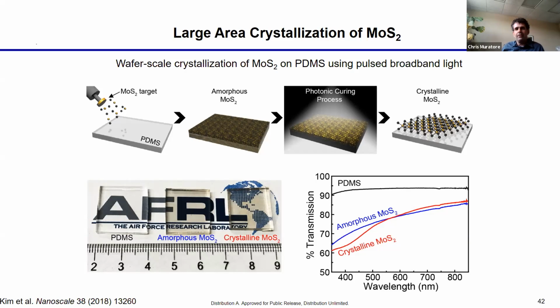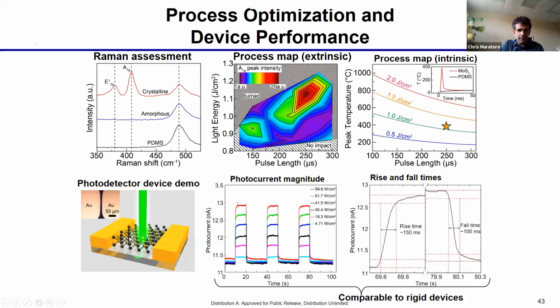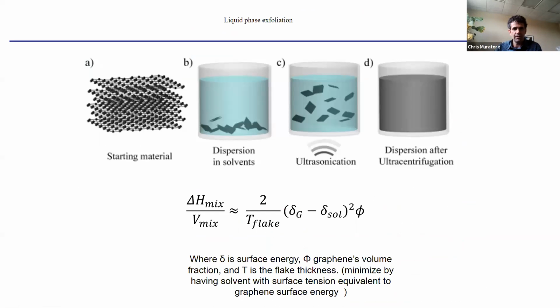You don't have to use a laser. You can use a broadband source, like a xenon lamp, as an optical source. And you can expose the amorphous material to energy in the form of this light and crystallize it over a much larger scale simultaneously, right? So you can do this over a square meter. You could buy a commercial photonic curing system that will anneal a square meter at a time, and you can convert these materials from amorphous to crystalline to give you properties such as light detection, right? So we've turned it into a semiconducting material, so we introduce some energy and we can induce a current to promote motion of electrons and use this as a photoconductor.